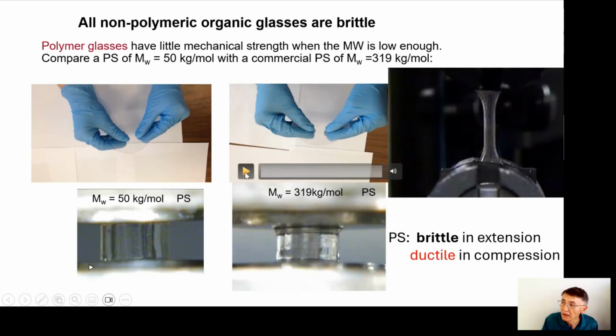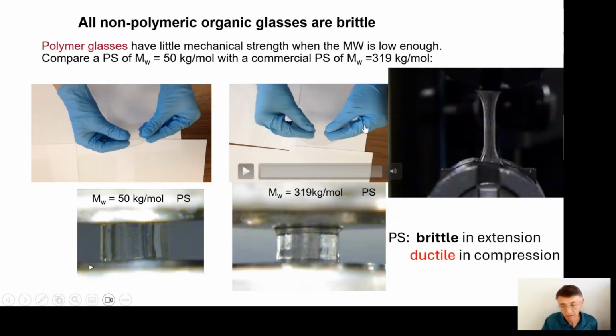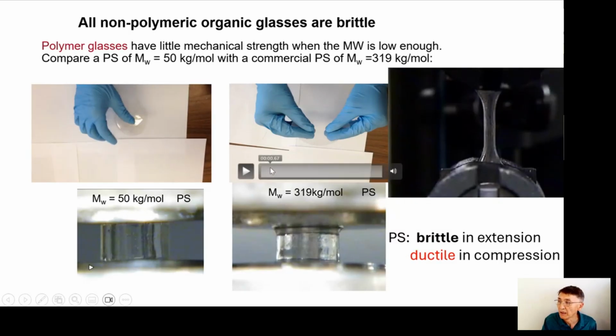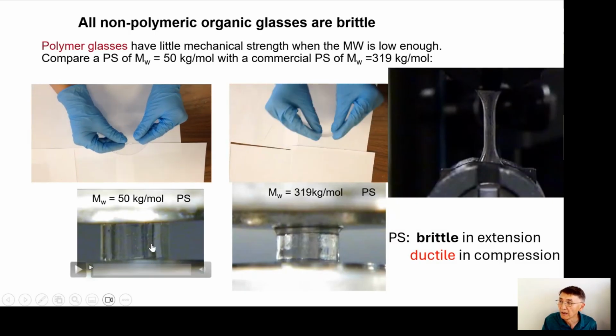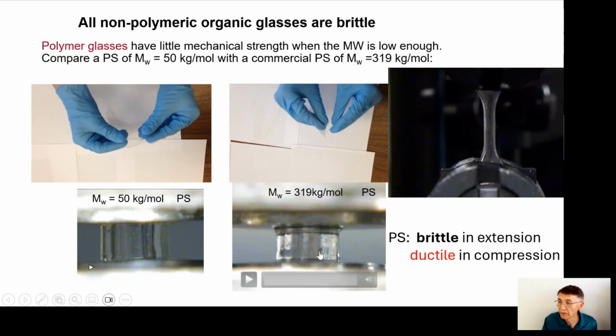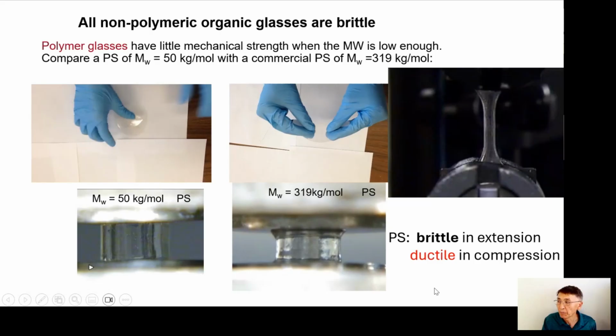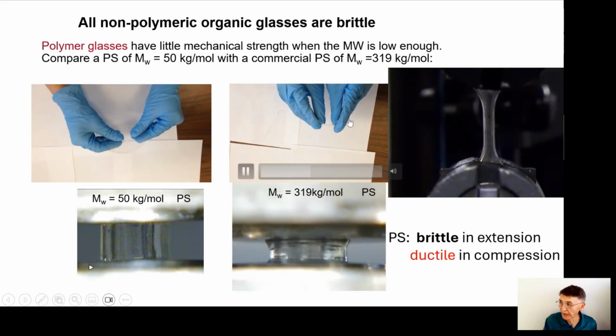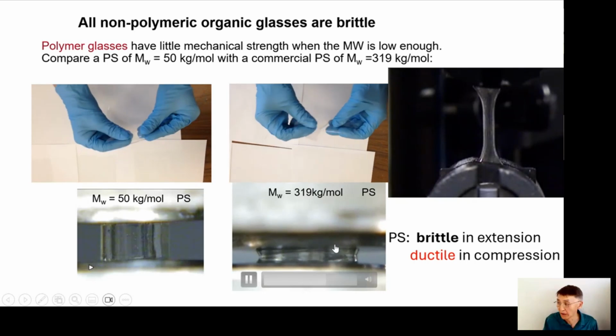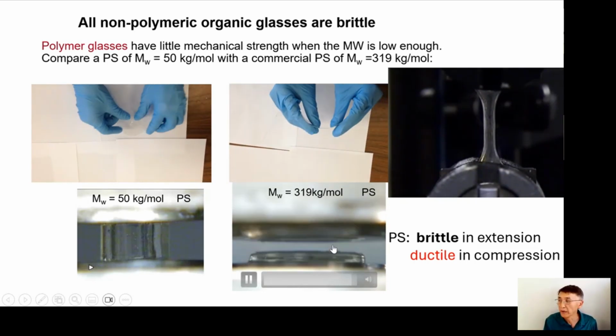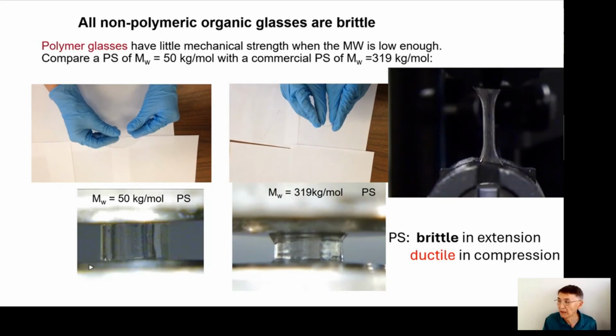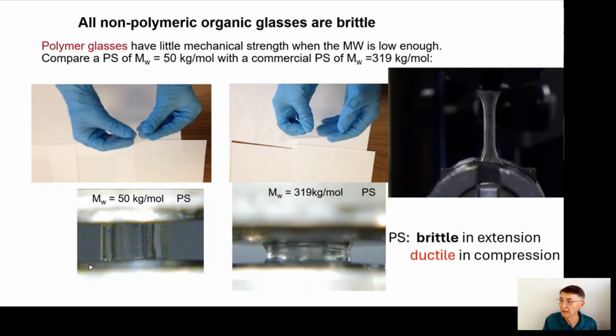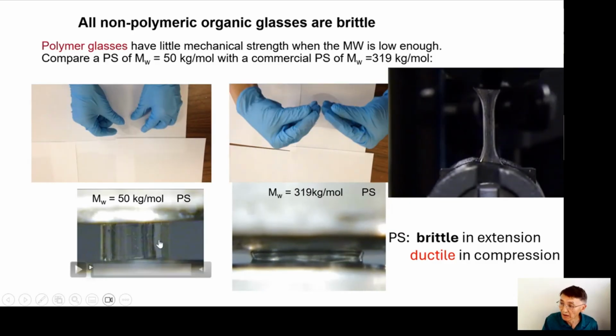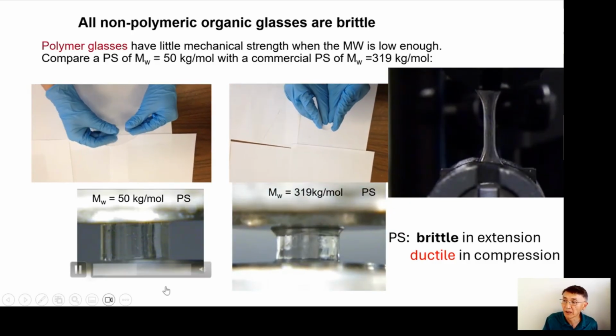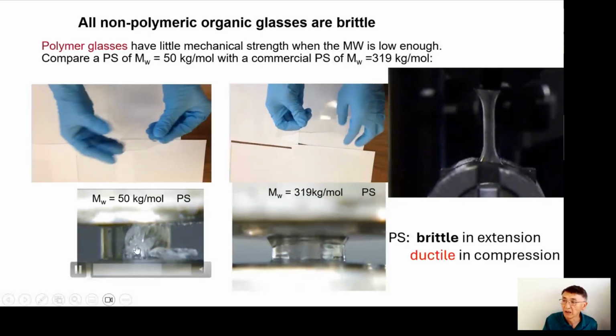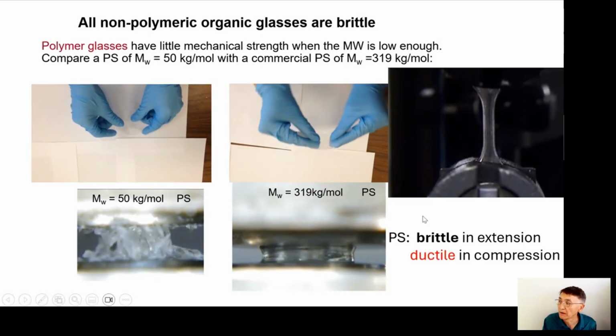I want to emphasize one thing: the reason we have to have high molecular weight is that without it, the sample is very fragile. One of the things to entertain you is to show you that polystyrene that is very brittle, as you can see from the bending, is totally ductile in compression. So I think we understand, among the first, why this occurs. It has to do with pressurization causing the polymer to turn ductile. But molecular weight is still important. If you have a molecular weight of only 50K for polystyrene, even compression gives you a brittle response.